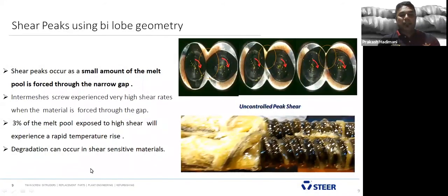What is peak shear we are talking about? When bilobe elements, two lobe, connect, you see here, in this area, the first zone, there's completely molten material, stagnant. You have a complete pool of the melt, and when it is going to the next level, here and here, the gap is going narrower and narrower. There are hardly 3% of melt trapped in between the two lobes, and that leads to peak shear that liberates higher temperature, and it degrades the polymer.